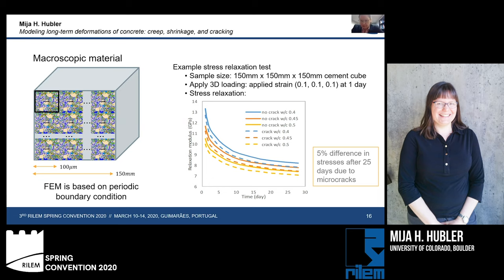And we assume that we always have some microcracks in our cement. But this effect is on the order of adjusting our water cement ratio from 0.4 to 0.45. If we now were to superimpose the cracks due to drying on top of these cracks, then we might end up with an even greater difference in our stresses that is being ignored due to the presence of the cracks.